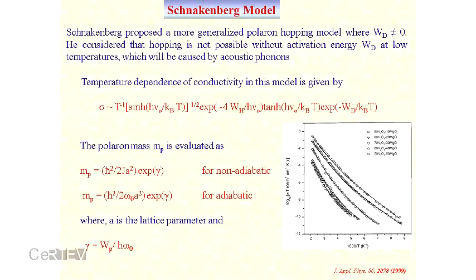And there are other models. I do not like to describe all of them. In Mott's model, one of the deficiencies is that it only considers the optical phonons, but it does not consider the acoustic phonons. Here, this model also considers some acoustic phonons at low temperatures, and derived an equation like this. And you can see this model also predicts a coupling parameter between the phonon and the electron. This is the electron-phonon coupling parameter, and then they differentiated the hopping as either non-adiabatic or adiabatic.